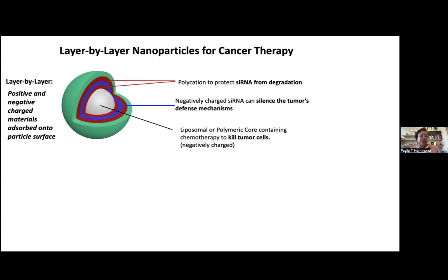So we want something that is going to be very hydrated as well, because that means it's going to be less likely to absorb proteins because there's a barrier, a penalty for proteins coming along and displacing these water molecules that thermodynamically are so happy associated with our layer. So there are a number of ways in which this becomes a stealth layer, a layer that causes the nanoparticle to go through the bloodstream without being rapidly recognized by immune cells and eliminated.